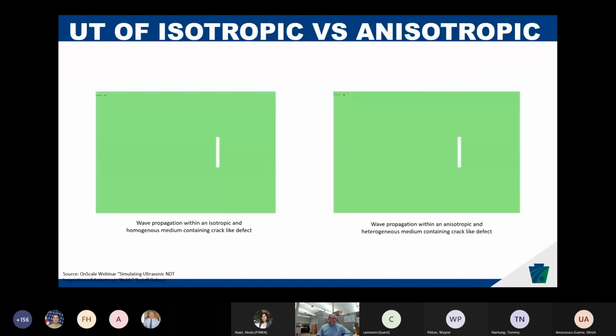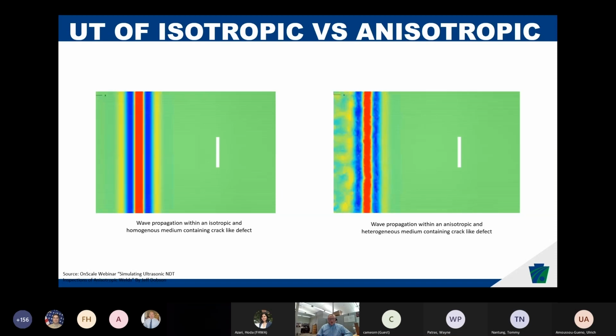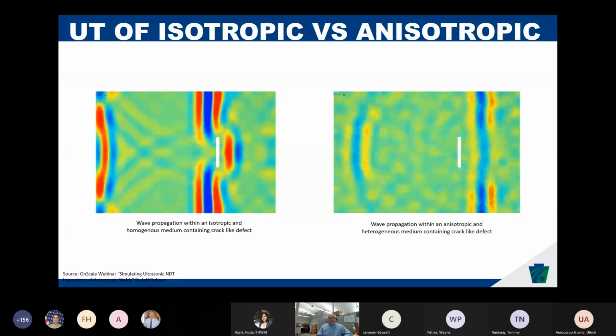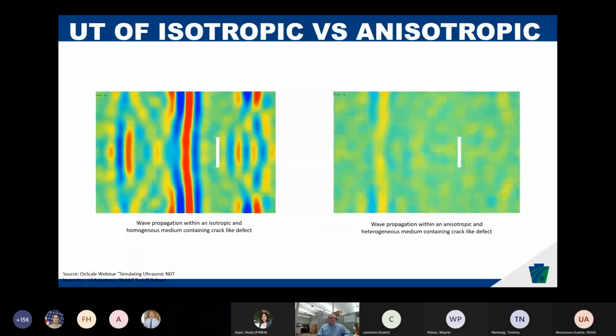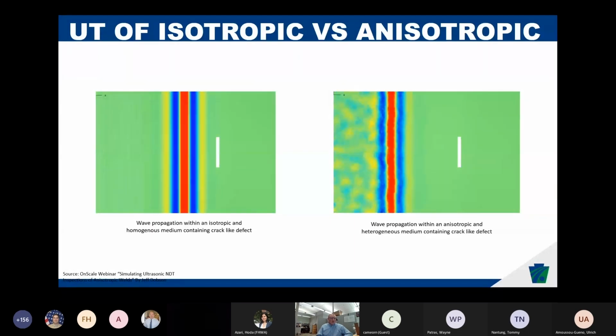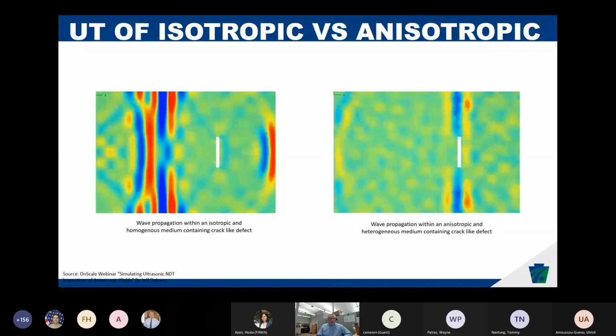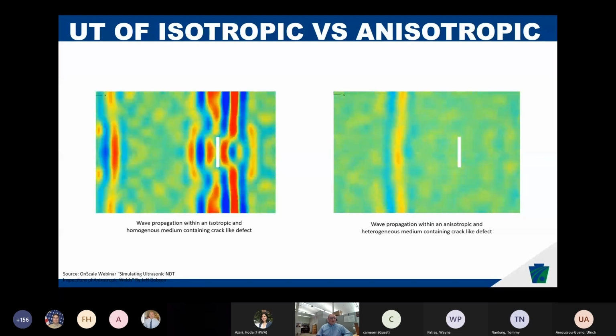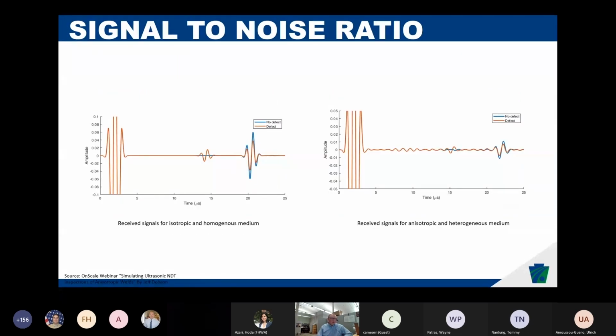So what that looks like, right? On the left is an isotropic material, on the right is an anisotropic material. And what that looks like is that you would have a large scattering effect, a large distortion of the wavefront, ultimately resulting in lack of signal response from a reflector. The signal to noise ratio is just not there. So it makes it very difficult when you're looking at an A scan to actually pick out any type of discontinuity. So it's something that has to be considered as part of the calibration process. It has to be considered as part of the scan plan process. What type of steel you're actually testing? What are the material properties?